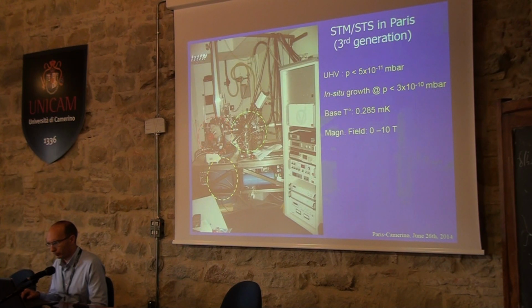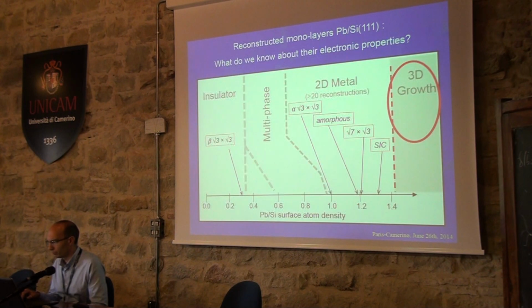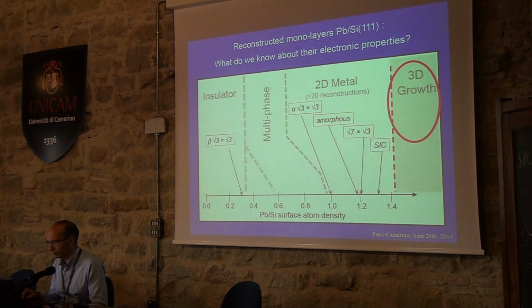So, in order to study these monolayers, of course, you need very drastic ultra-high vacuum conditions. Specifically, you cannot get your samples outside of the UHV chamber, so you should combine a deposition chamber, a characterization chamber, and an ultra-low temperature STM in ultra-high vacuum. So, I start with the superconductivity in islands.